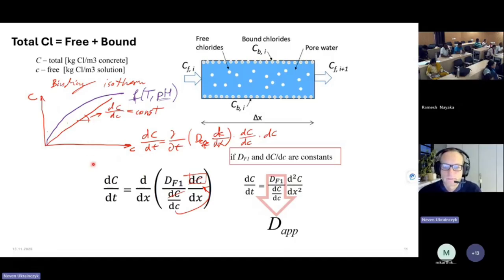That's why the LC3 system, when you put the clay system, in general any mixture with clay which has aluminates and is reactive, improves the durability, not only because of the pozzolanic reaction, which creates more CSH, which again binds the chlorides and refines the pore structure, so it's changing the effective diffusion coefficient and also making more binding. But you also have more calcium aluminates like Friedel salt that also more strongly at the beginning bind the chlorides.